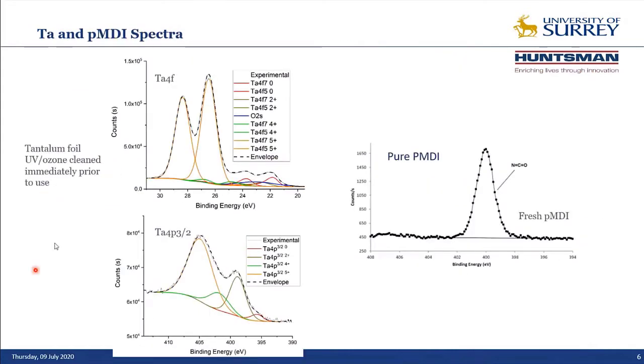On the screen now, we've got on the left-hand side a tantalum 4f spectrum of our tantalum foil sample, and we can see that the oxide is fairly thick. The spin orbit splitting of the 4f is very clear. The peaks are really quite slim, very intense because the cross-section of the 4f is very high.